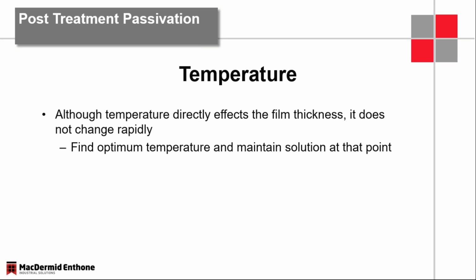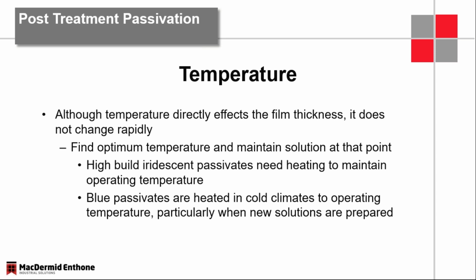So yeah, it needs to be maintained. It can be maintained, but things like the environmental situations like cold rinse waters need to be monitored as well. So the thicker, higher film iridescent Passivates are usually heated to higher temperatures, while blue Passivates are not. You want to take the chill off of them in the winter times and when you're making up new solutions.